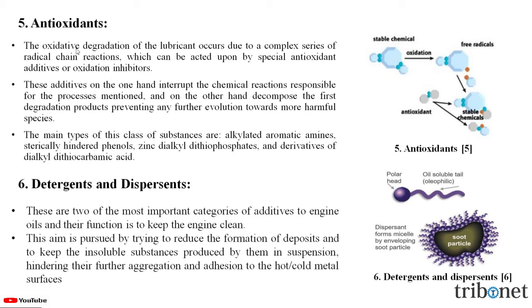The fifth one is antioxidants. The oxidative degradation of the lubricant occurs due to a complex series of radical chain reactions which can be acted upon by special antioxidant additives or oxidation inhibitors. These additives interrupt the chemical reactions responsible for the process and decompose the first degradation products, preventing any further evolution towards more harmful species. The main types are alkylated aromatic amines, sterically hindered phenols, zinc dialkyl dithiophosphates, and derivatives of dialkyl dithiocarbamic acid.